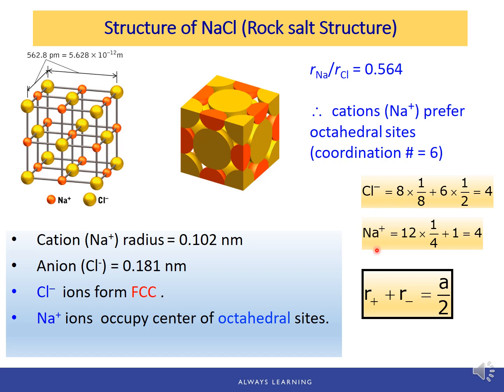And for the cation, which are at the edge of each unit cell, we know each edge is shared by 4 unit cells, so 12 times a quarter, plus there is 1 in the body center, which just belongs to this specific unit cell. So the number of cations in one unit cell is also 4. So the ratio is 1:1 for the sodium chloride. And we can also get the lattice parameter.